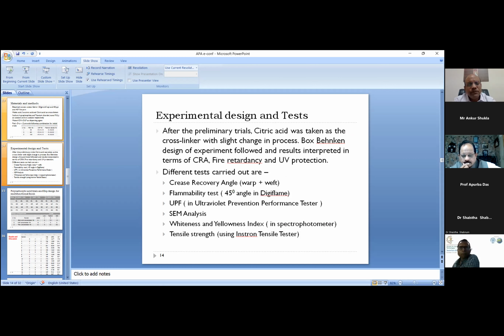So that is what is mentioned here. And the different tests carried out were the crease recovery angle, the CRA or anti-crease effect, then fire retardancy by flammability test, then UV protection by UPF, the ultraviolet protection factor, measured in an ultraviolet prevention performance tester by Gester, and then the SEM analysis, whiteness, yellowness, and then tensile strength.